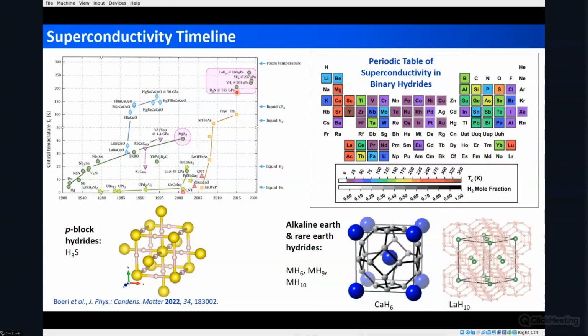it looks like here. And then 1 year later, this lanthanum H10 compound was made by two different groups, Eremets and Hemley, and its TC was measured. And again, this was actually theoretically led, so the theory came first in this case, predicting that lanthanum H10 would be a very high temperature superconductor. And other compounds, such as calcium H6, were predicted and then eventually made, though the synthesis ended up taking later. And then MH9, Julia talked a lot about YH9, so that's another well-known prototype structure for a number of these high-pressure compounds.